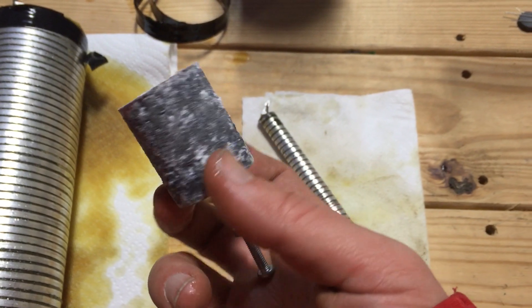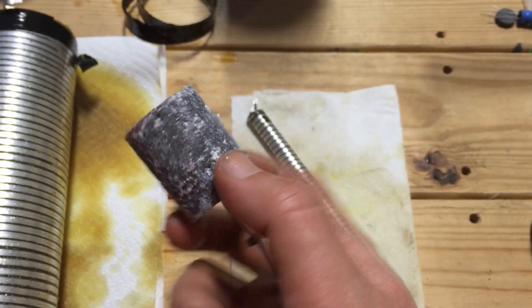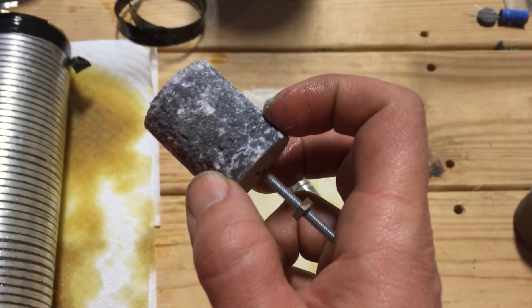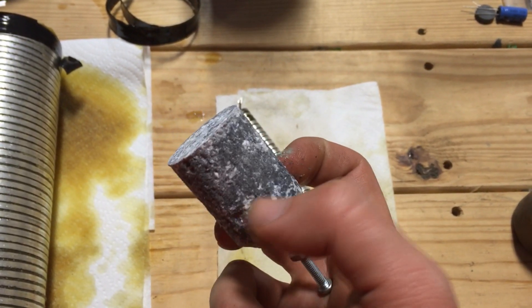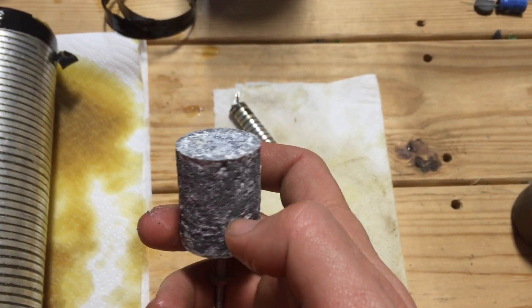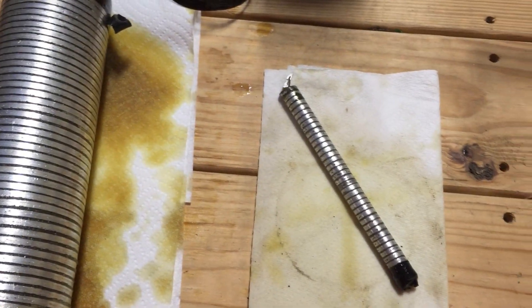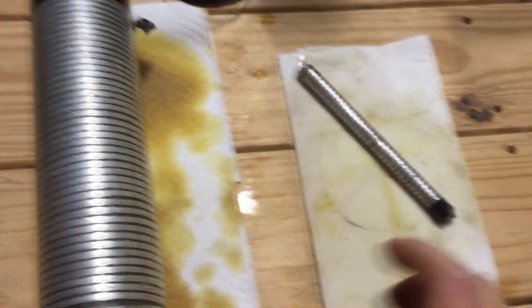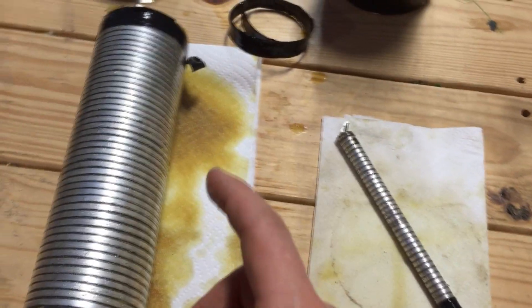I have a sample of magnesium rod here so you can see the pitting that normally goes on in a crystal cell configuration. As the crystals grow into all the little holes, the crystal growth just keeps advancing into the magnesium, keeping good contact between the anode and the cathode. The magnesium being the sacrificial anode just slowly gets eaten away, but in this oil configuration we've slowed that down a lot. So if you had a small motor or something you want to run for an incredibly long time, this may actually work pretty well.